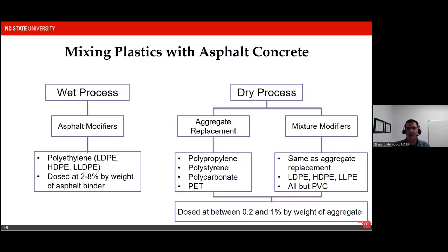There's also a set of processes where we use them as mix modifiers. In this case, we basically introduce them into the mixing drum, even though we realize that those materials may melt through the process. So we'll blow in the high density or low density polyethylene, and then we'll just let it melt into the mix and use it as a normal mixture modifier. And in these cases, the dosage rate is quite a bit lower, but it's also done by the weight of the aggregate. So we're using 0.2 to 1% by weight of aggregate, whereas the wet process, we're using it by weight of binder. So it's a little bit of an apple and an orange kind of comparison.